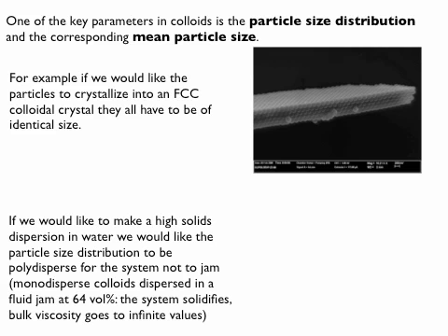So if you want to make a dispersion that has higher solids, you have to start playing with the particle size distribution. You can imagine, because you've got gaps in there, and we saw it before, that typically a gap between three particles in 2D would be 0.15 times the radius of the spheres that you've used. You can imagine that if you use different ratios of different particles, you could get the overall solids up so it's still a liquid.